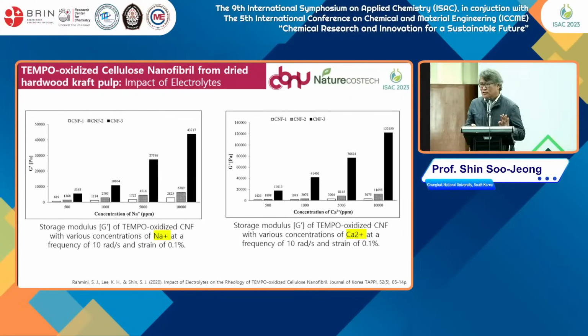When we increase the cations, they increase the gel strength. Divalent cations come from calcium. They increase gel strength up to an optimal condition, but when we put too much of the divalent cation, they start to decrease the gel strength. So if we control the amount of cations, we can make much stronger gels, like sodium alginate.